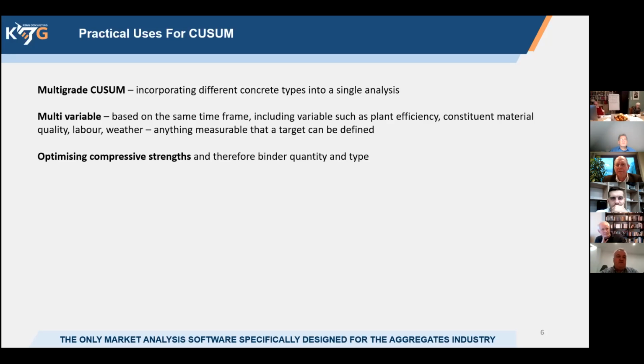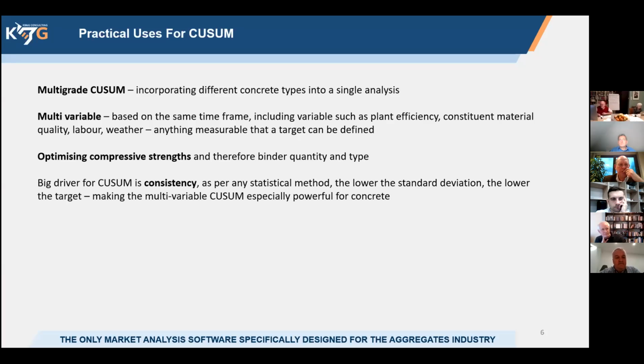And then obviously optimizing compressive strength and therefore binder quantity and type. If you're trending too high all the time, obviously you can remove binder. That's the loose link to CO2 in this particular presentation. But the big driver for CUSUM is consistency. And we all know that the more consistent your product is, the more economic it is to make and the more surety you have on the end result. So that's one of the reasons why it becomes especially powerful in concrete.